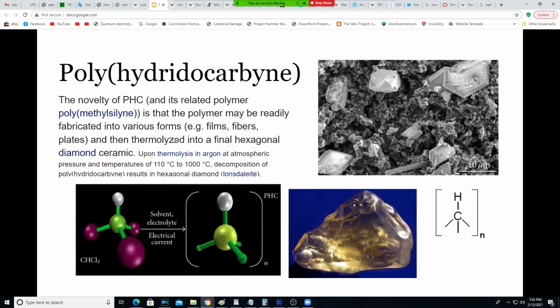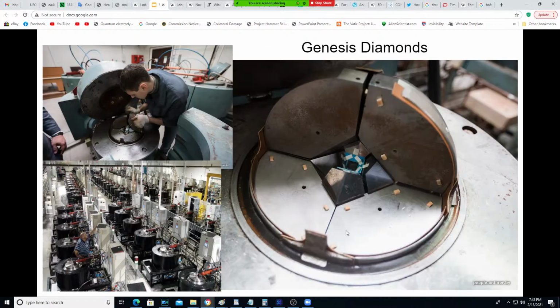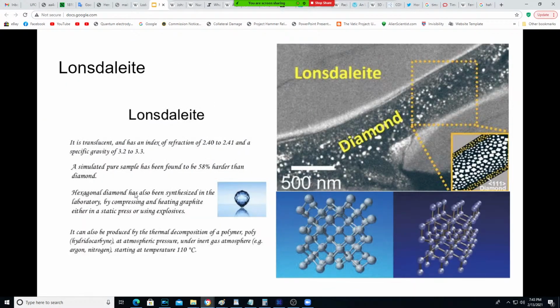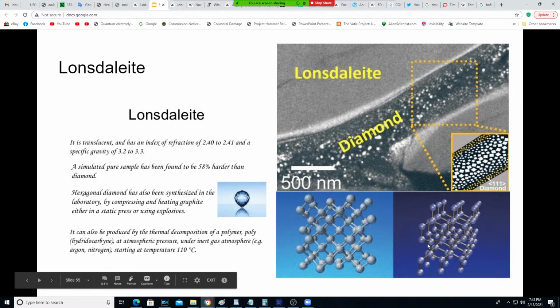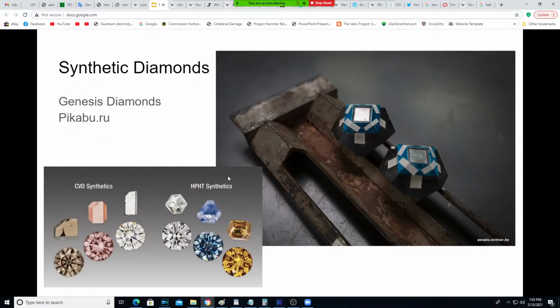There's also printable diamond, this stuff called poly(hydridocarbyne), or PHC. It's a polymer that may be readily fabricated into various forms, like films, fibers, plates, and then thermolyzed into a final hexagonal diamond ceramic. Upon thermolysis in argon at atmospheric pressure at 110 degrees Celsius to 1,000 degrees Celsius, decomposition of poly(hydridocarbyne) results in hexagonal diamond or Lonsdaleite. Lonsdaleite, as you know, is a translucent diamond. It's about 58% harder than a natural diamond, and synthetic diamonds are produced by a number of companies in a number of different ways.